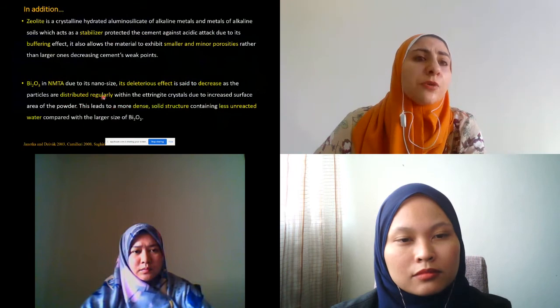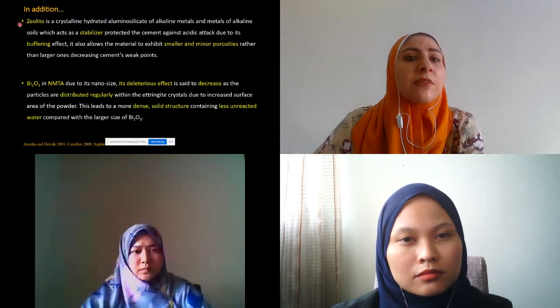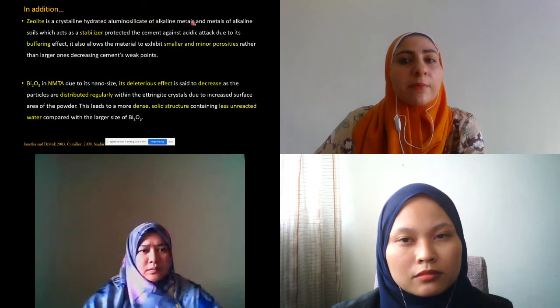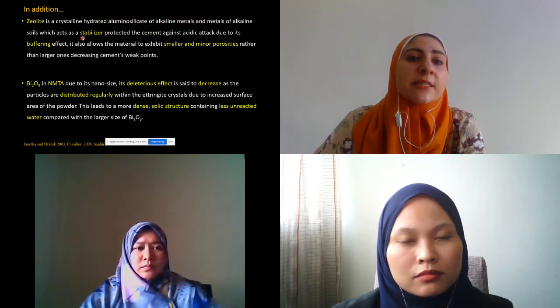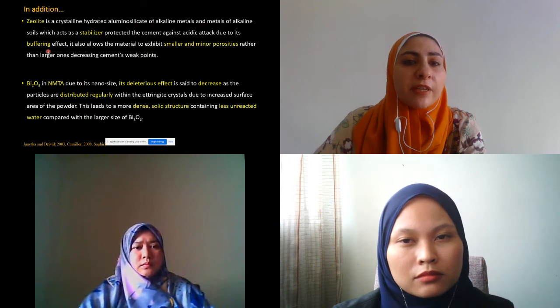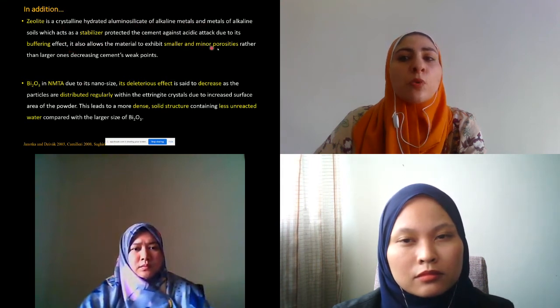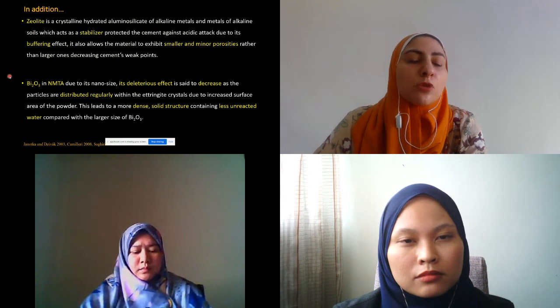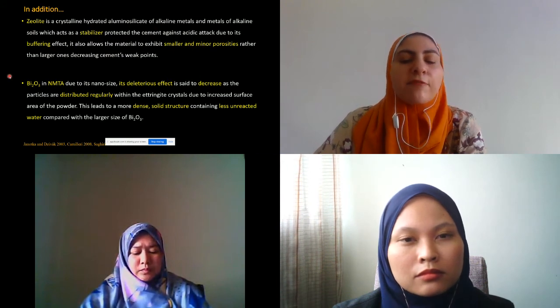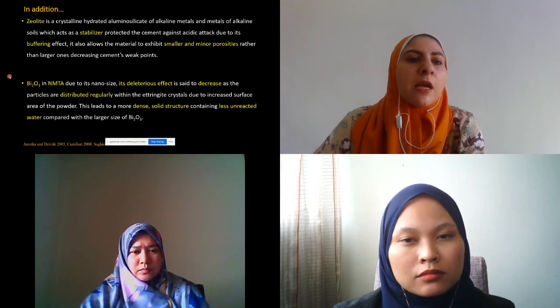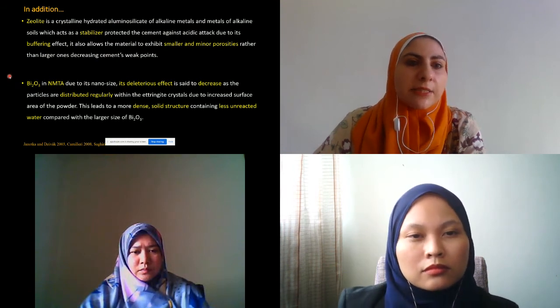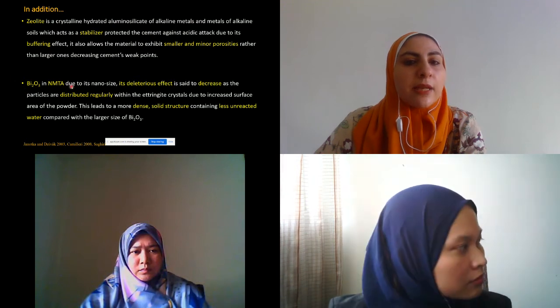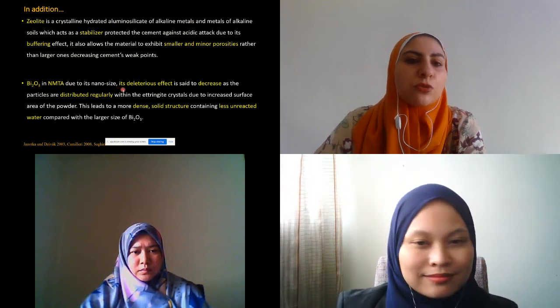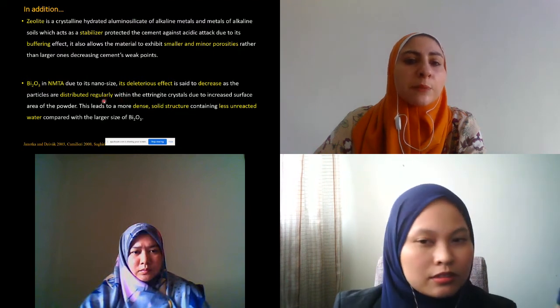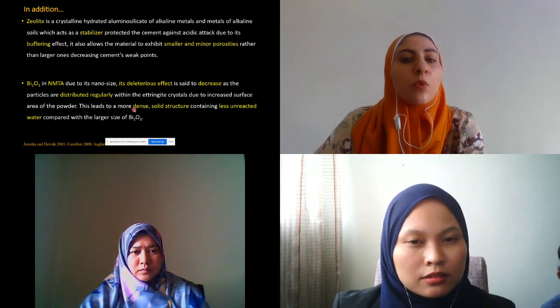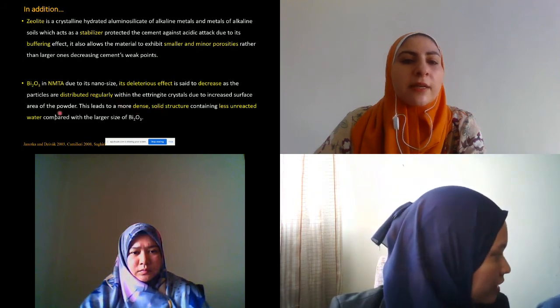In addition, zeolite, which is added to Nano-MTA, is a crystalline hydrated aluminosilicate of alkaline metals and metals of alkaline earths, which acts as a stabilizer, having a buffering effect, allowing the material to exhibit smaller and minor porosities. Bismuth oxide is added to MTA or Nano-MTA for radiopacity. In its biggest size, it has a deleterious effect. But in nano size, it showed that it has no deleterious effect due to the decrease of particle size, which makes it distributed regularly, resulting in a more dense structure and less unreacted water.